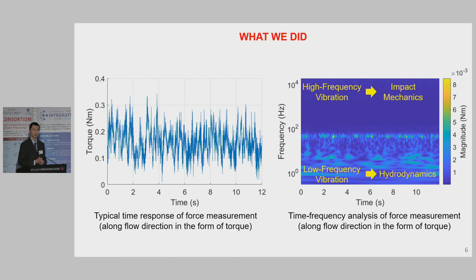Here is a snapshot of how we process the signals. The figure on the left side shows a typical time response of force measurement, where you can clearly see the probe vibration. When we transform the signals into time and frequency domain, we can see energy concentrates at low frequency regime, where we apply hydrodynamics to extract drag coefficient and flow viscosity from the measured flow-induced drag.